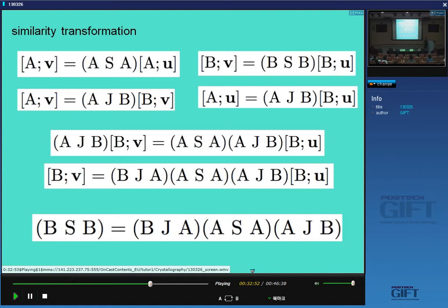So this is a powerful result. We've done a transformation of a deformation from one coordinate system to another. Now you'll see why this is important. Because some deformations we can just derive a deformation matrix by inspection, because the axes happen to be aligned along certain directions. But in reality, we might want to express the deformation in terms of another frame of reference, and then we just do a similarity transformation if we know how to change the coordinates.